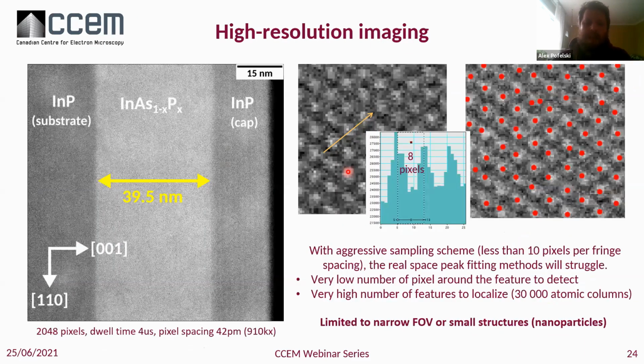But what happens if you have slightly larger devices, where you don't have just nanoparticles where you can even count the atomic columns? What about, for example, this thin film sample that we just talked about when we presented the sample preparation, which has this 40 nanometer thickness? Because of its size, we need to reduce the magnification a little bit, and by reducing the magnification, we affect the sampling scheme. Before we had 29 pixels, now we drop to something like 8 pixels in this type of image.